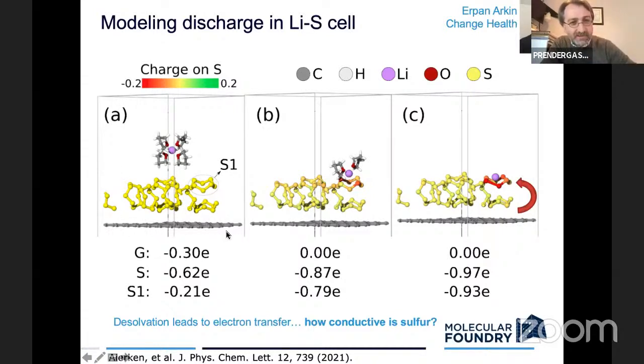So we have graphene as a model of our current collector, the active sulfur sitting on top of that in a thin layer. We'll get to thicker layers later. And then we imagine this thought experiment of bringing a lithium cation from solution down to the surface. And then what we notice is that initial charge that was localized on the graphene, maybe with some hybridization with the sulfur, ends up moving to this region near the lithium ion, and eventually the local sulfur molecule here is what gets reduced. That picks up this extra electron that was initially on the graphene and sits right beside the lithium. Okay, looks fine. One question you might ask is, how conductive is sulfur?